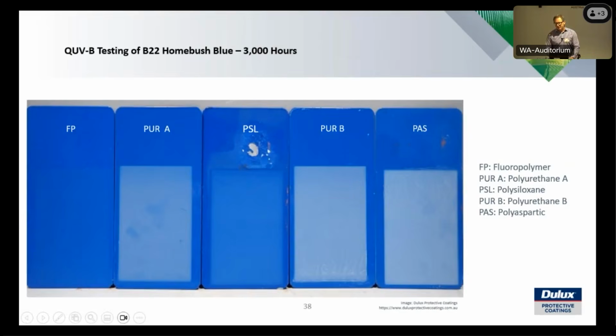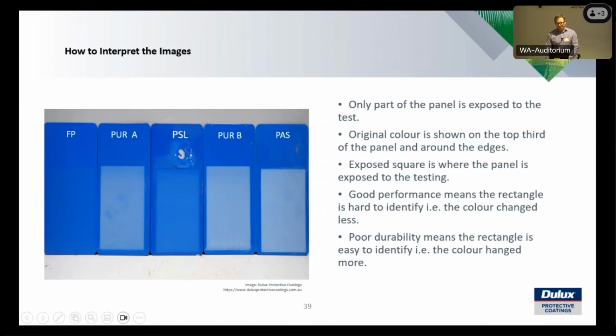But after 3,000 hours, you really start to see some changes there. With the PSL, I'm not too sure why it was damaged during the testing. I'm not too sure what's happened there at the top there, but you see the polyaspartic and the urethanes are really starting to lose their colour after 3,000 hours in this test. But remember, this is a really harsh test as well, but it's really digging down on the resin system of this test. Just how to interpret it.